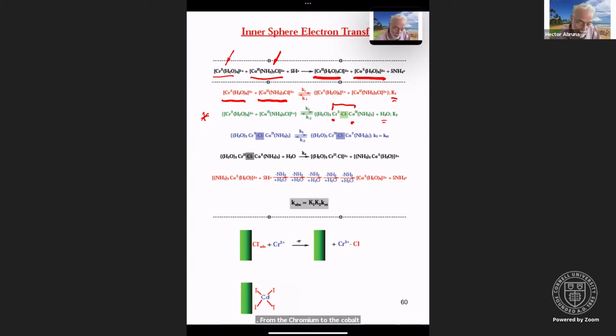So the chromium goes from chromium 2 to chromium 3, cobalt goes from cobalt 3 to cobalt 2. And that's an inner-sphere electron transfer. And then there's a series of very fast reactions where all hell breaks loose. But now the chloride gets transferred over to the chromium. And then in rapid sequence, because this is cobalt 2, it's substitutionally very labile, all of the amines come off, and you end up with hexaquo cobalt 2 and the chromium pentaquo chloro. And so a couple of things. One, reactants and products are very different.